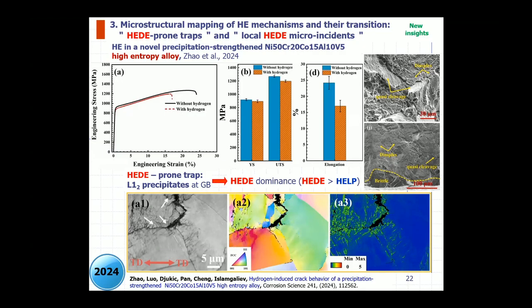So what's the idea? To change the design principle to avoid that type of precipitates, which are good for strengthening of this alloy and for corrosion resistance of this alloy, but not good for hydrogen. And we carefully investigated that HEDE-prone L12 precipitates at grain boundary, which is a very dangerous location from the point of view of HEDE activation, is unbeneficial. So we have HEDE dominance, and HEDE is larger than HELP. As you can see, white arrow, we have a location of precipitates. As you can see, we have intergranular failure at the exact location related to this.